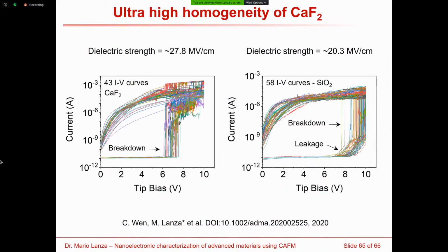And we also performed one additional experiment, which was to scan again, to repeat the IV curves at different locations, but in this case, using the logarithmic preamplifier provided by this AFM. And what we could observe clearly is that the calcium fluoride shows sudden dielectric breakdown for all the positions analyzed. And if we calculate the dielectric strength, because we have the electrical field applied and also we have the bias applied, and we also know the thickness, we can calculate the dielectric strength.